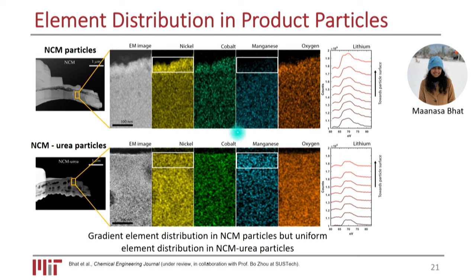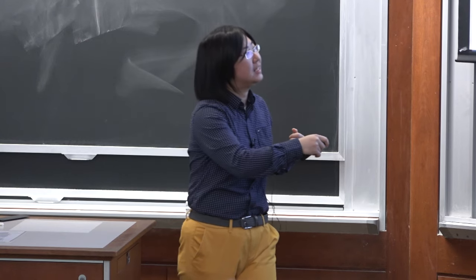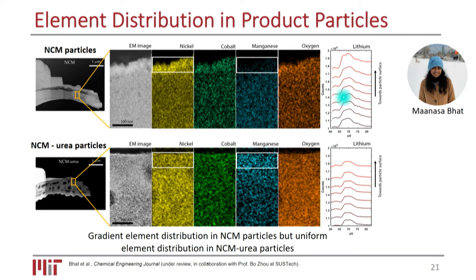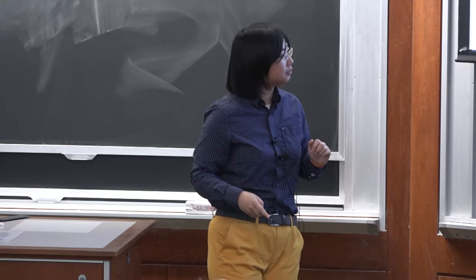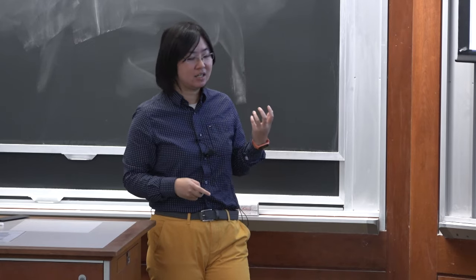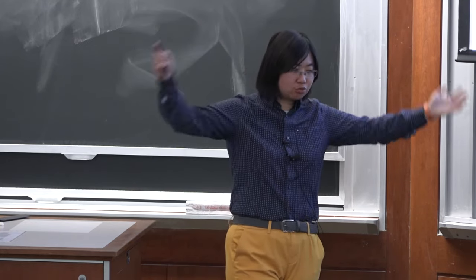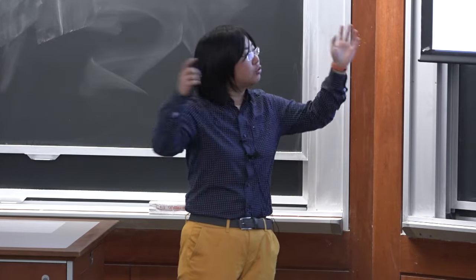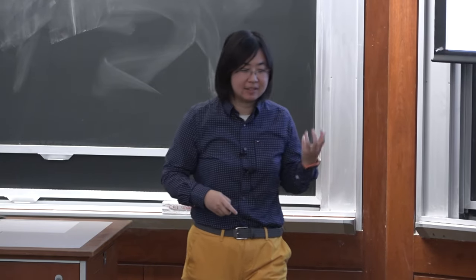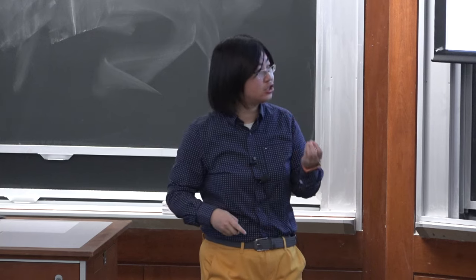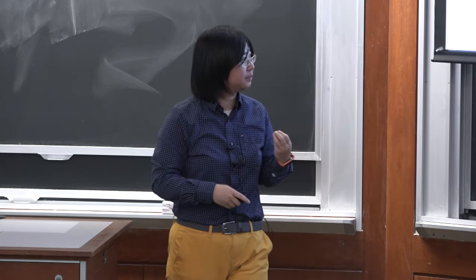And because mass has to be conserved, we do see less of the manganese component compared to the center. So is the lithium. We do see a gradient structure in the lithium distribution. Whereas generally speaking, in the NCM with urea additives, the distribution is more homogeneous. So we want to understand why adding urea helps us distribute lithium and other elements such that we can get the same performance with much, much shorter calcination time.